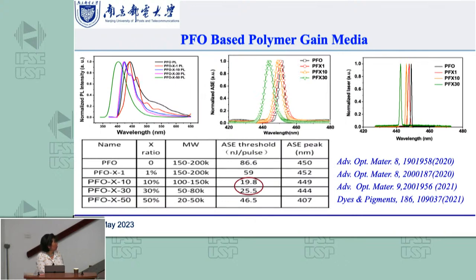So this is PFO material we buy from a commercial company. Then we add what we call the DP side chain. The laser threshold can reduce to one third or a quarter, with just a very small amount. But if you add too much, the spectrum will shift, and that's what we don't want. So this is one possibility to reduce the threshold. We have demonstrated that.